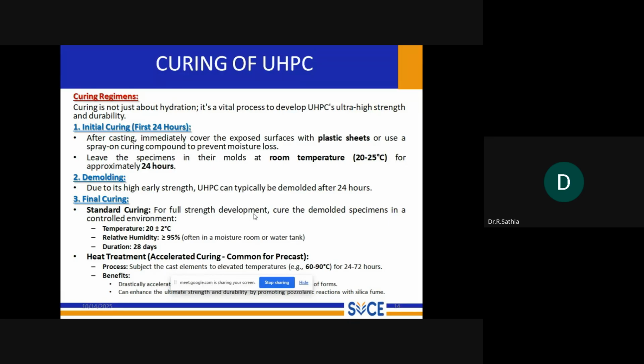So the curing is done immediately by covering the exposed surface with a plastic sheet or by spraying a compound to prevent moisture loss. Then the mold is kept at a room temperature of 20 to 25 degrees for 24 hours. After that, it is demolded, and the final curing is done at a temperature of 20 degrees and a relative humidity of greater than 95%, or in a water tank for 28 days.